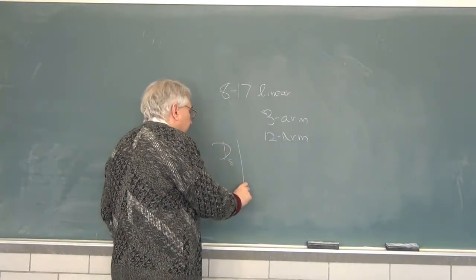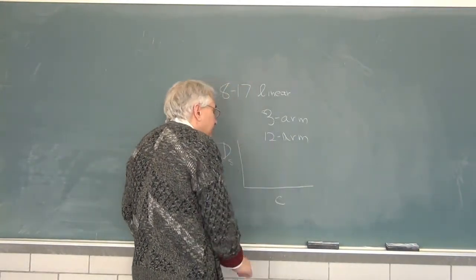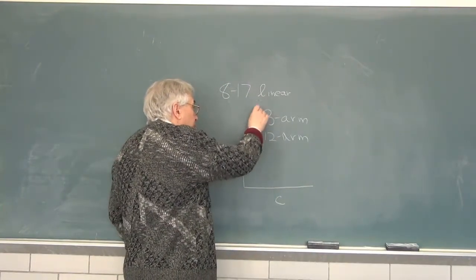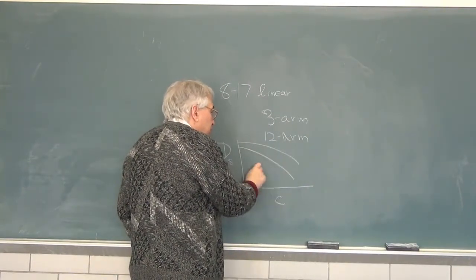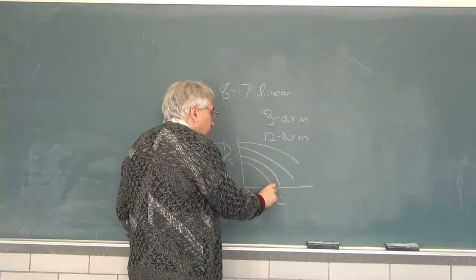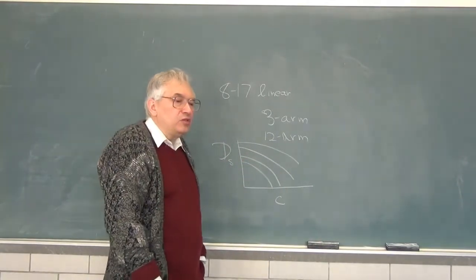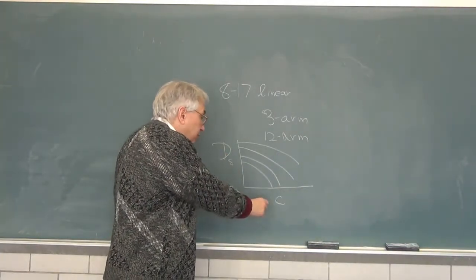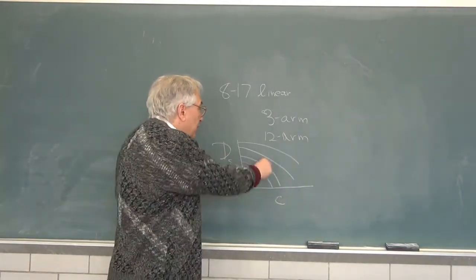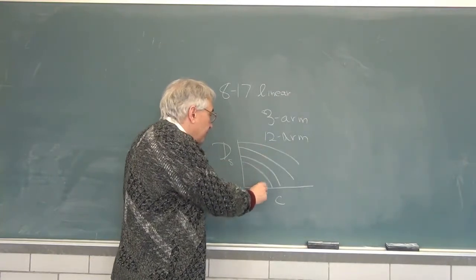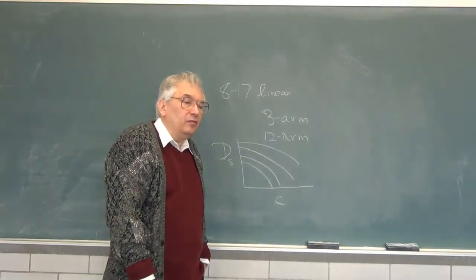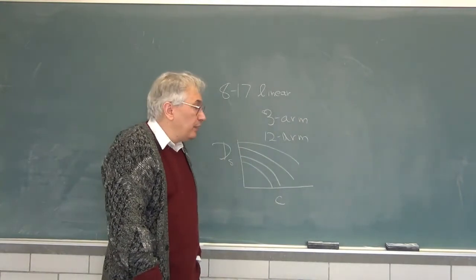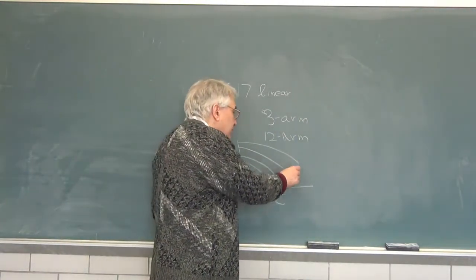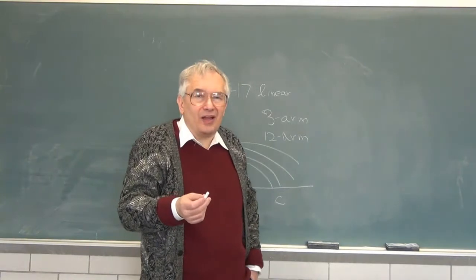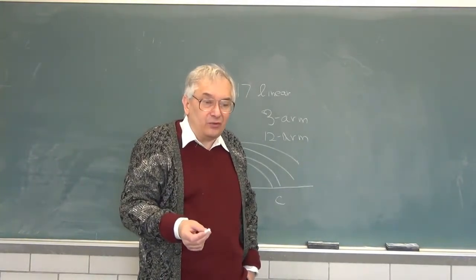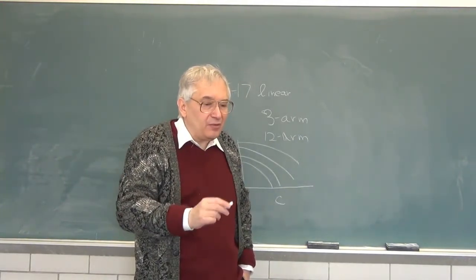DS versus concentration. And we can do this for a series of different probes, and of course the larger probes diffuse more slowly. And we get measurements of D of the probe versus concentration of the matrix for four different sizes of probe. Well, that's very nice. And if you look at the graphs, you'll see these nice lines that really do a fine job of going through the data points. They really do, with a couple of exceptions I will get to.